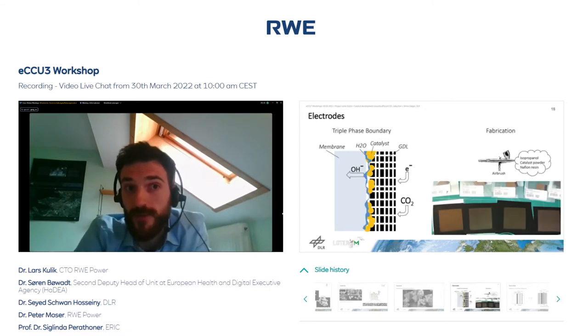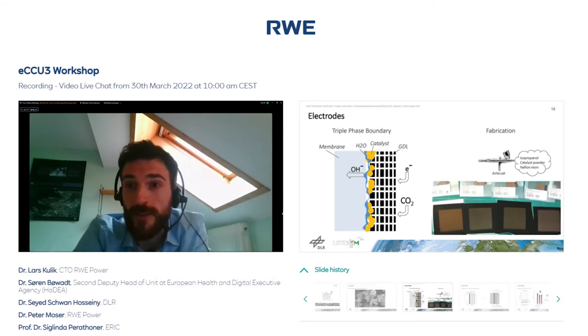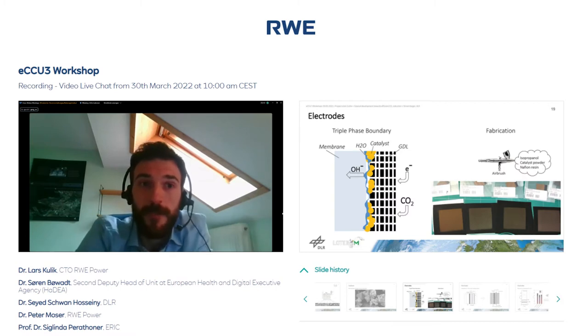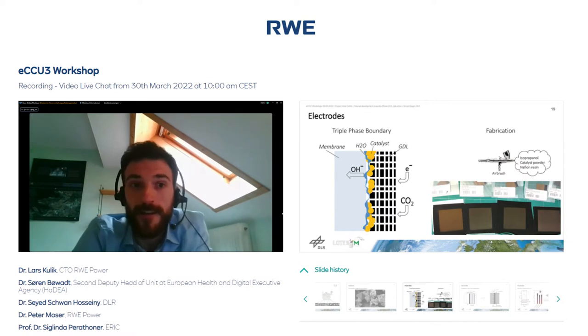So this brings me to the last part with electrodes. We have here on slide 19, shown on the left side, an overview of what is really necessary to produce successful electrodes. And this is the so-called triple phase boundary that is very important here, meaning three phases have to be present on the catalyst at the same time.